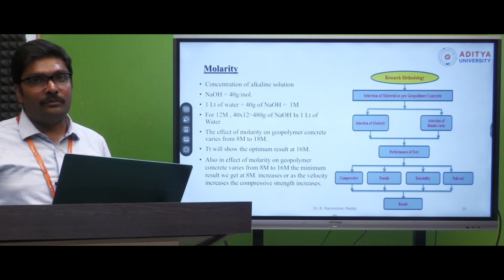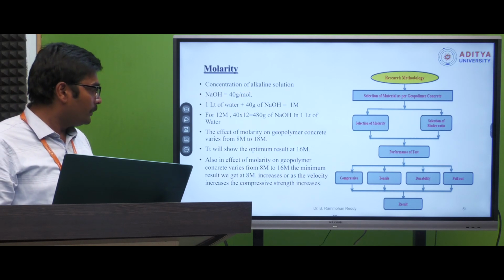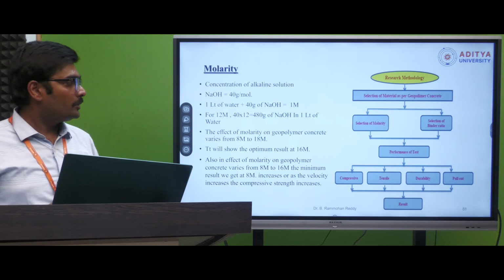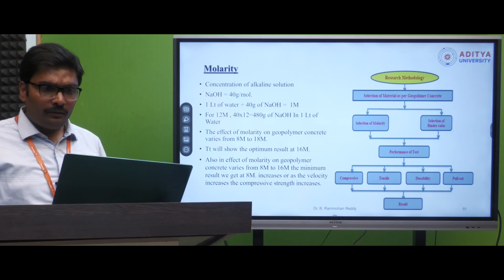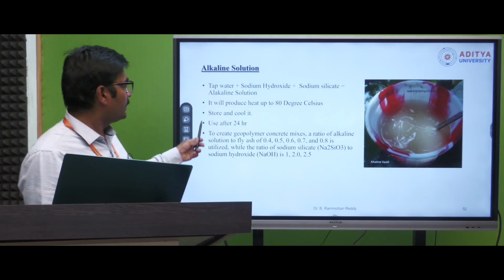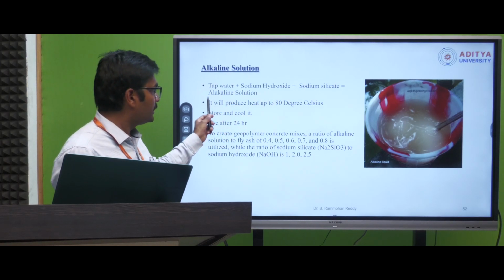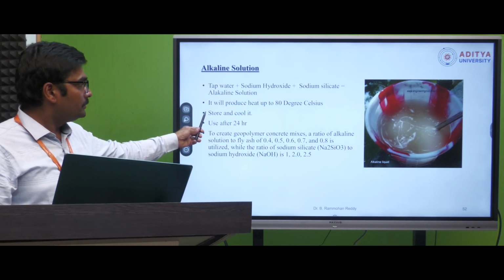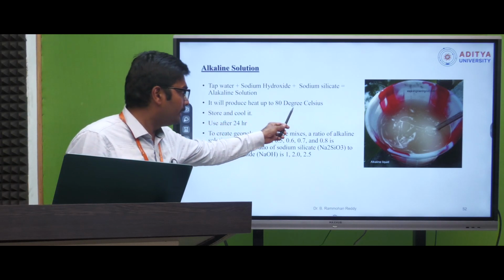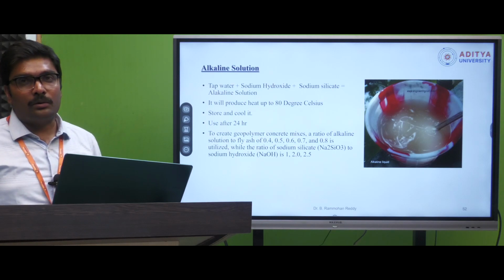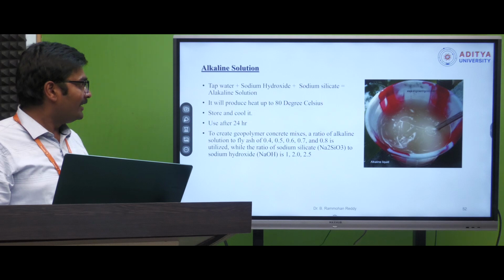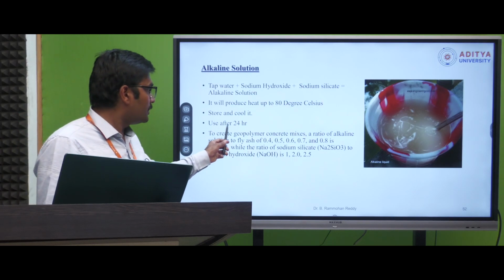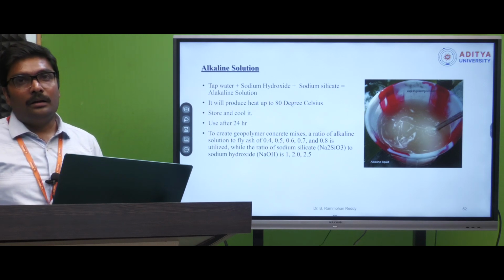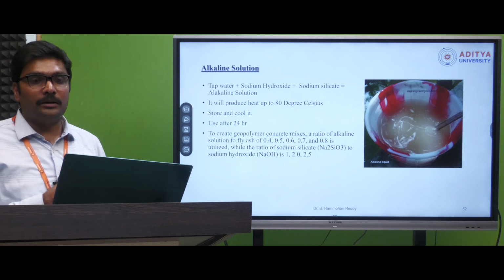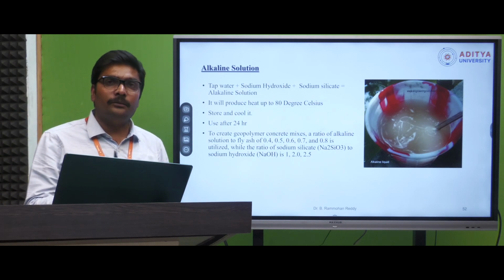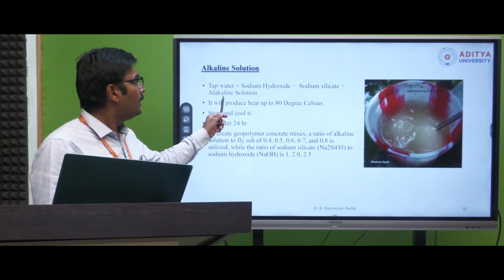But we need to take care while adding sodium hydroxide pellets, because it will produce heat while adding it, so better to check that and add carefully. And in this slide, if you can see, water, sodium hydroxide and sodium silicate will give alkaline solution. And you can see it will produce heat up to 80 degrees Celsius, so we need to store this solution in a cool place, and while preparing sodium hydroxide solution we need to take additional care and use after 24 hours. So this is also a major point. So if you are planning to cast the samples today, or today if you are planning to use geopolymer concrete in the construction, it means 24 hours before we need to prepare this alkaline solution.